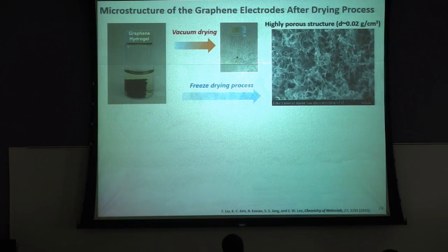Then we can also control the microstructure of these graphene electrodes. If we dry this graphene hydrogel by vacuum drying, it shrinks into particles, so it is hard to make an electrode with this kind of particle. So instead of vacuum drying, we use the freeze drying process, and we can preserve this porous structure. But the density of this electrode is too low, 0.02 gram per cc, right? As I mentioned, density is also an important parameter for designing electrode materials. The density of a commercial activated carbon electrode is around 0.7 gram per cc.